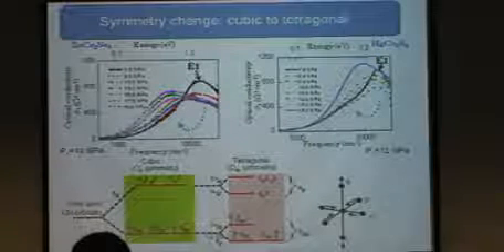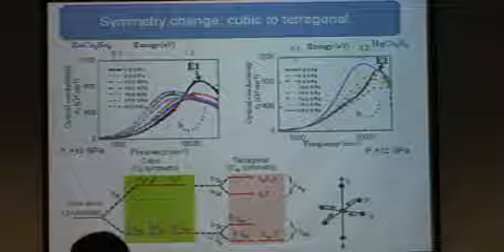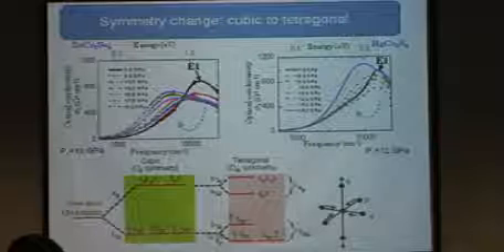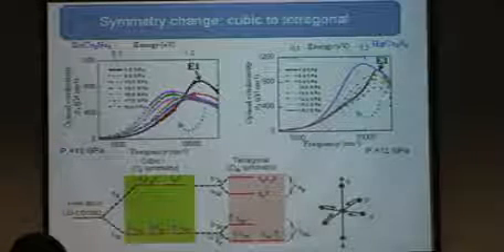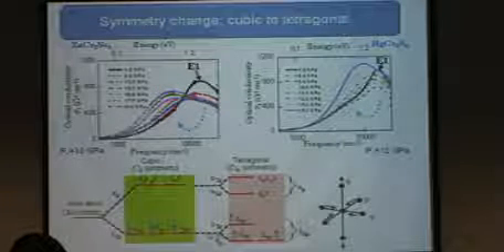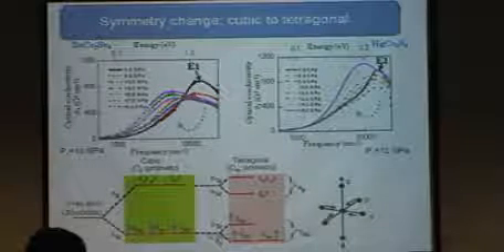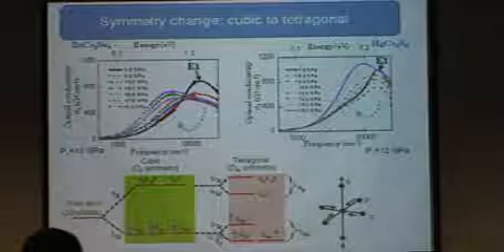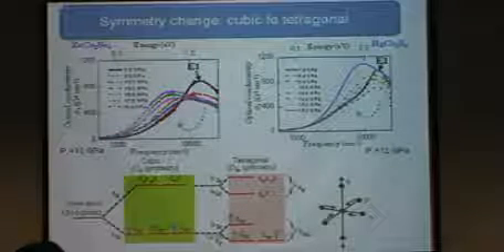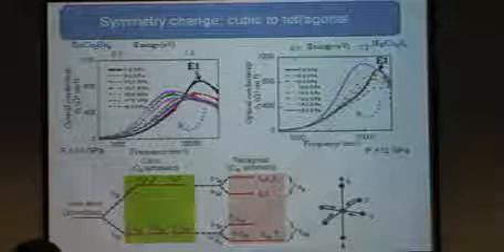From this infrared data, I can't tell you. For this, one has to go for XRD. It's just, you can say, a tentative interpretation. The point is, if your spectral weight is moving toward low frequency, one chance is it is going to be metallic. But then if you look at the low frequency side, you don't see any Drude term. So that's why this delocalization is over. That's my own interpretation. Even that data is not published yet. It's just ready for submission.